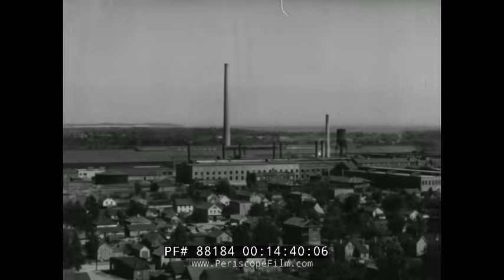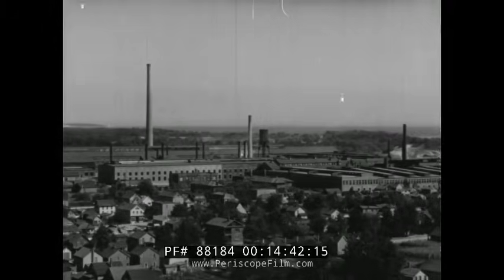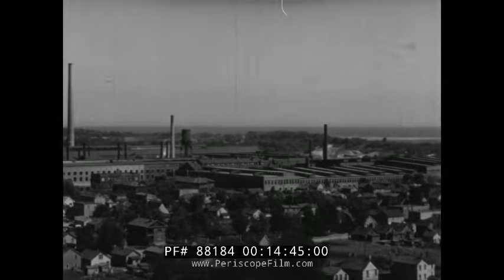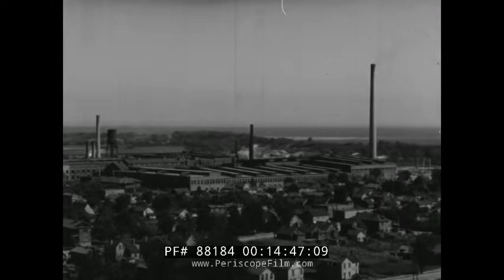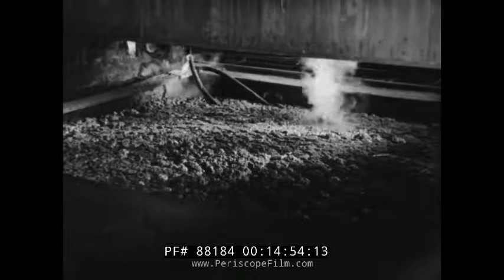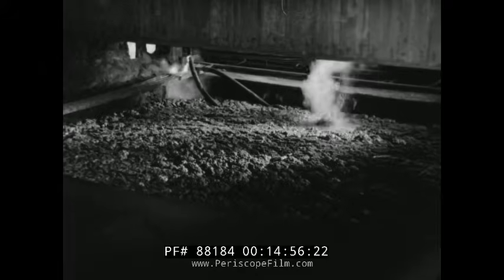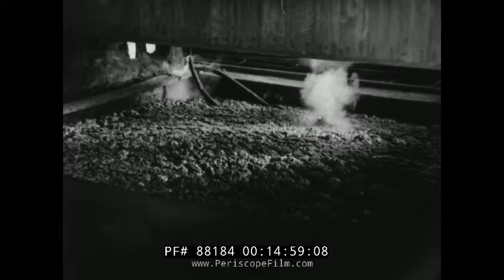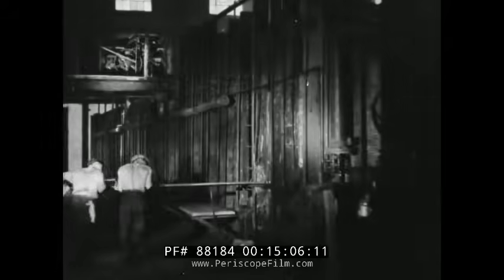The Port Colborne refinery is located at the entrance of the famous Welland Canal. Here the nickel bottoms from the Copper Cliff Orford process receive their final treatment. The bottoms are first crushed in the ball mills. The material is then loaded into large tanks where it is leached, washed, and dried. This product is called washed nickel sulfide. Some of the sulfide is roasted twice in long calciner furnaces. The first roast drives off a large part of the sulfur, and the second roast leaves the material practically sulfur-free. It is called black nickel oxide.